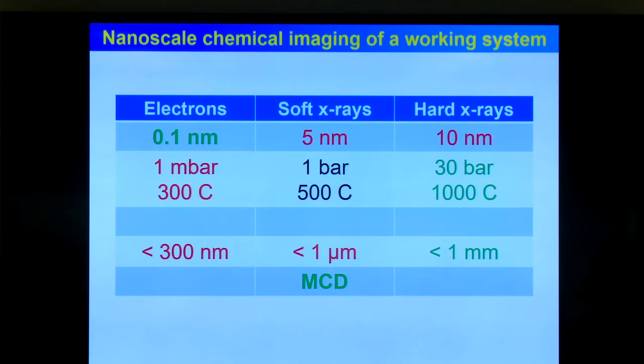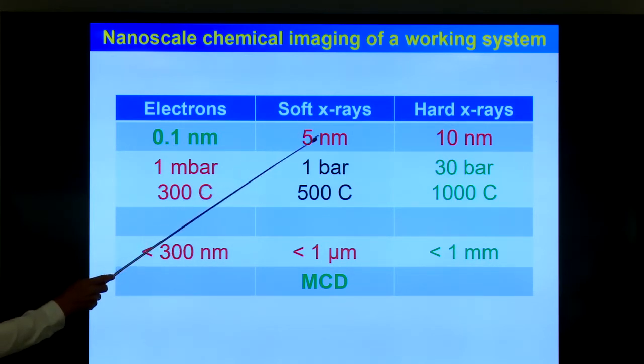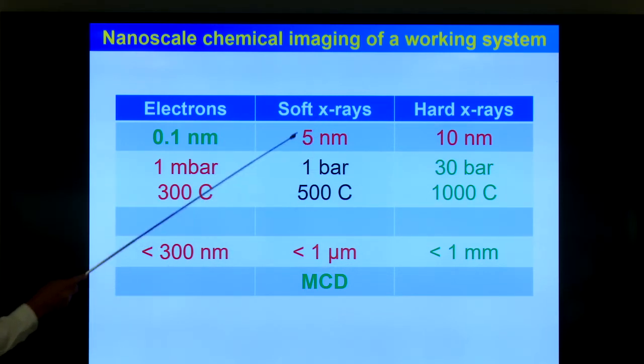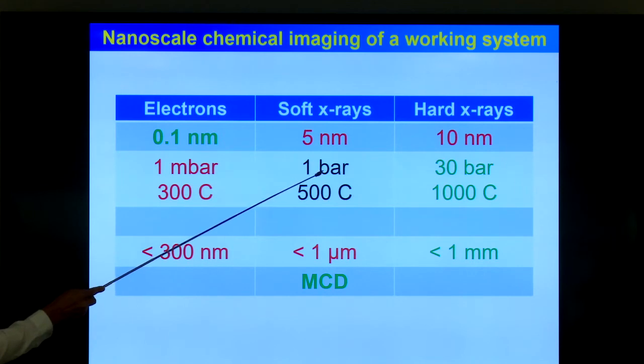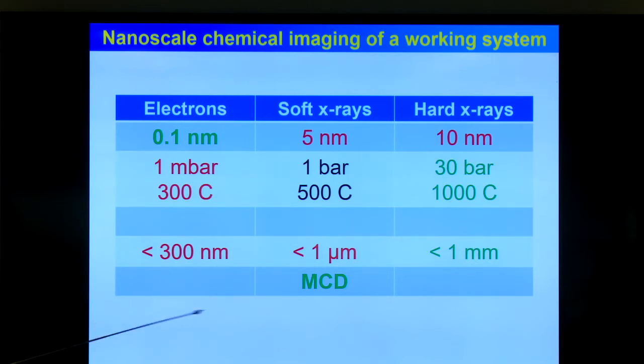And then to compare the different advantages and disadvantages of the different sources. If you have electrons, an electron microscope, your resolution is what you want, so atomic. But your pressure and temperature are a little bit limited. I mean, there are systems where the pressure is higher, but it's difficult; standard electron microscopes don't go above 1 millibar and 300 Celsius. And your sample must be very thin, less than 300 nanometers. With soft X-rays, the resolution is 5 nanometers. This is an old slide, but I think that's still a valid number. You can go to 1 bar, you can probably now go to 5 bars and a little bit higher temperatures, but still your sample must be very thin, less than 1 micron.